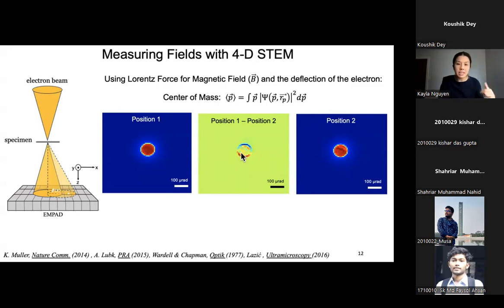And here, what you can see is that as we subtract these two diffraction patterns, we get changes. It goes from red to blue, or it goes from top to bottom, depending on what you choose your direction, of how the electron beam is deflected by the local magnetic field.